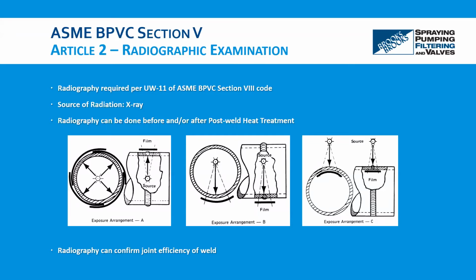Thank you, Nicco. As per ASME Section 8 Division 1, there are many instances where full radiography is required, given in UW-11 as stated here. Most likely for all the butt welds of pressure vessels which are used to contain lethal substances. All the butt welds in which your nominal thickness exceeds certain thickness based on the P number of that material. Like for carbon steel material, table UCS-57 provides various thickness criteria in which full radiography is required. Most commonly used carbon steel material like SA516 grade 70 need full radiography when its nominal thickness is more than 1¼ inch. Also, full radiography is required in steam boilers when your design pressure is more than 50 psi.